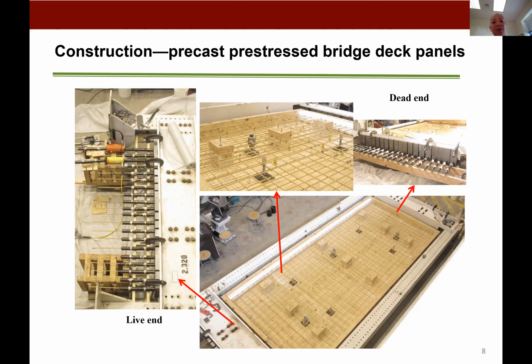Before I transitioned, they actually did a full scale test where they just did a lap splice with these bars and were able to use conventional pre-stressing equipment. So it can be done even in the field, although we just used a single hole jack for pulling on the AFRP bars. Once we were able to pull on them, pour the grout into the pipe, and lock in the stresses so we could get the achievable pre-stressing tension that we wanted, we cut the strands. That took about 3 hours per strand for all 20 of those concentrically pre-stressed strands. Then of course the top and bottom grids were laid with non-pre-stressed bars.